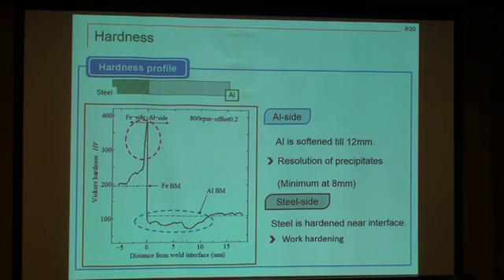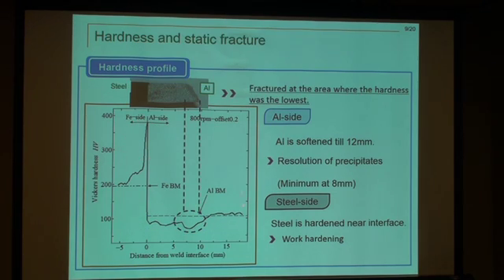And this is the hardness profile in the cross section of the joint. As you see, the hardness increased in the steel side near the interface. We think that this is due to the work hardening effect. And as you see in the aluminum side, the hardness decreased. It is due to the dissolution of the precipitates because this material was heat treated beforehand. And this is a macroscopic appearance after the tensile test. And as you see, the fracture occurred at the area where the hardness decreased.